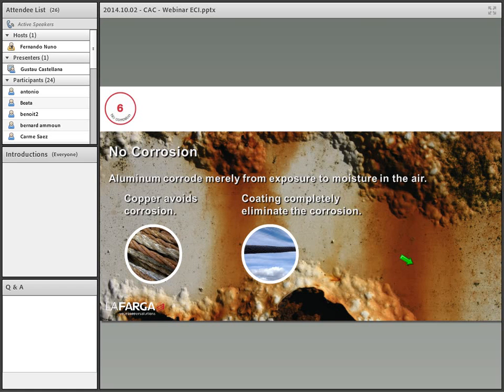As you know, copper avoids corrosion compared with aluminum. Against corrosion, it behaves a lot better. If we add the coating on the conductor, we almost eliminate the corrosion. There are studies done in South Africa in real situations. They put ACSR and AAC solutions and compared them with copper, and the copper solution was 4 times better than the aluminum ones.